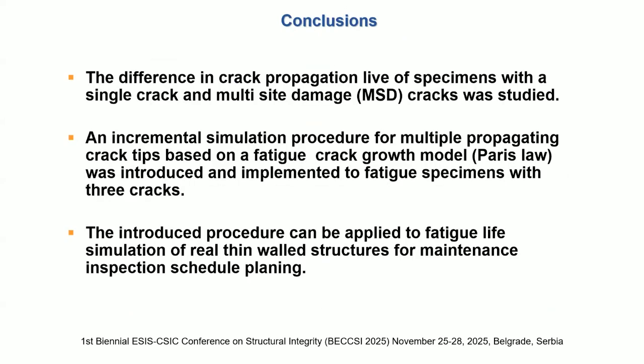Different crack propagation lives, especially with a single crack and multi-site damage (MSD) cracks, were studied. An incremental simulation procedure for multiple propagating cracks is based on a fatigue crack growth law model. In this case, the Paris law was introduced and implemented for fatigue simulations with 3 collinear cracks. This procedure can be applied to fatigue life simulation of thin-walled structures, such as ship structures or airplane structures, offshore structures, and other structures, and used for inspection schedule planning.